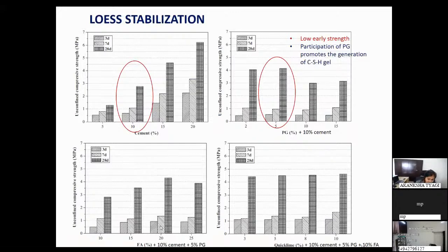Basically, fly ash is a material which needs to be activated. The low activity of fly ash requires it to be activated by the SO4 minus, which is present in the phosphogypsum. So this phosphogypsum is helping the fly ash to provide strength, to increase the activity of the fly ash. However, when there is excess fly ash, it is not getting reacted with the phosphogypsum. Only 5% of phosphogypsum was good with 20% of fly ash for this type of soil.